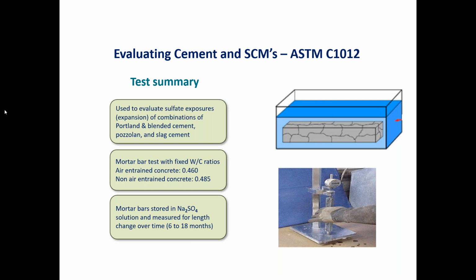In a lot of cases, these mortar bars can actually crack and break up, and I like this little representation on top. It shows a poor little mortar bar that's been sitting in the sulfate solution for a while, and it's started to crack and fall apart. But understand too that there are different specifications based on different scenarios for how much expansion is tolerable and within what time. The minimum time is 6 months. That's the minimum amount of time it would take to get your final reading, and the maximum time specified is 18 months. So this is a very long-term test. Next slide.